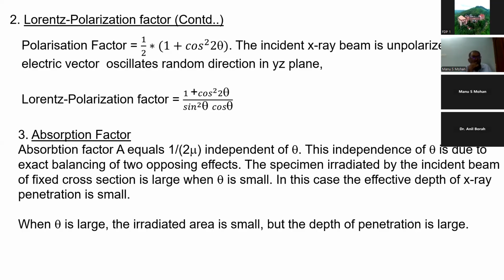Then you have the absorption factor, which is equal to 1 by 2 mu, where mu is the absorption coefficient, because when you pass X-rays through the sample, some of them are absorbed by the specimen.